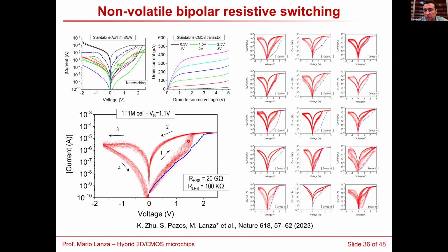Why? Because first of all, the resistance of each state is very high. The currents are much smaller than in the big device. Second, in the big device, we had sharp transitions, and here the transitions are quite progressive. So basically, these two factors are telling us that I don't think we are working in a filamentary mode. I think we are introducing some defects, but not producing the complete breakdown of the boron nitride.